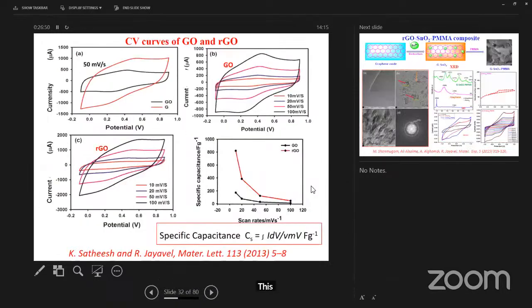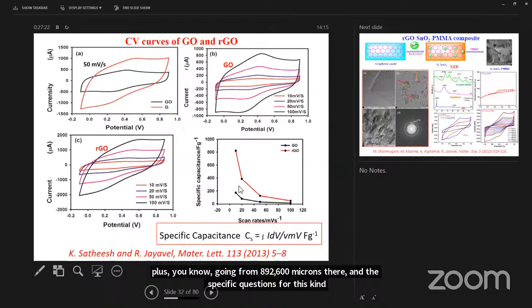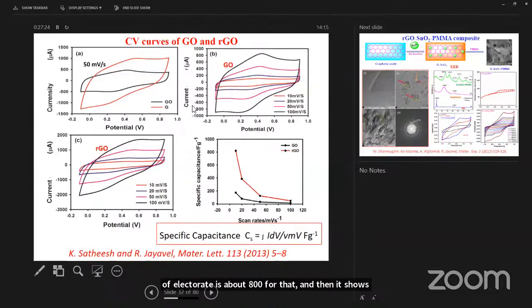There are different kinds of applications, but we are more focused on energy storage. Then we do the cyclic voltammetry of this one. If you look into the cyclic voltammetry of pure graphene oxide and RGO, the current value is almost double, going from 800 microampere to 1600 microampere. And the specific capacitance for this kind of electrode is about 800 farad per gram, which shows that the material can have a very high energy density, but the power density is limited because of the low current value.